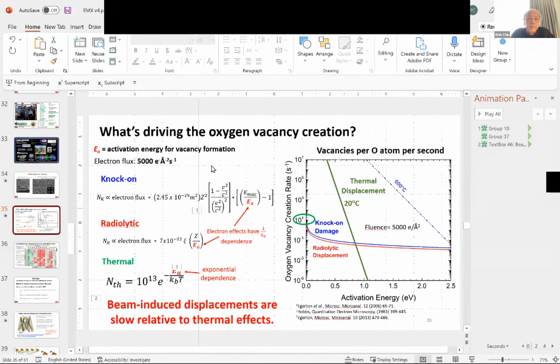Yes. So this is a very crude calculation, but this is for an electron flux of 5,000 electrons per second. And we're asking the question, it goes back to Bob's question about, does the electron beam create an oxygen vacancy? So if you think that the activation energy for creating an oxygen vacancy is EA, we can calculate the probability, the cross-section for the electron transferring energy EA through a knock-on process or through a radiolytic process. All the equations are in the literature. So what we're doing here is calculating the number of oxygen vacancies created through knock-on, and the number of oxygen vacancies created through radiolysis.